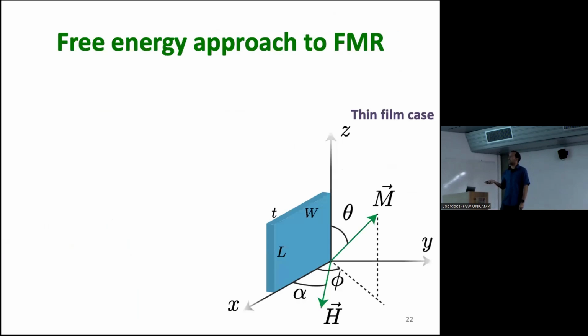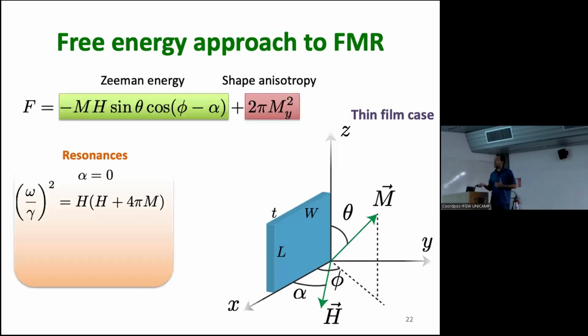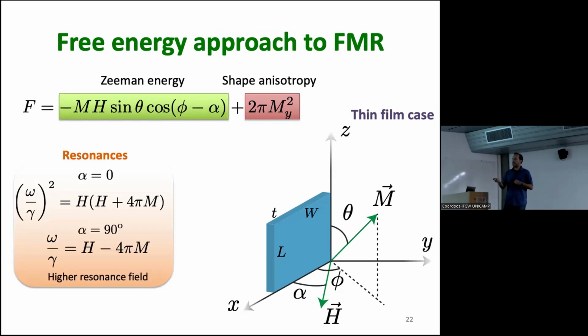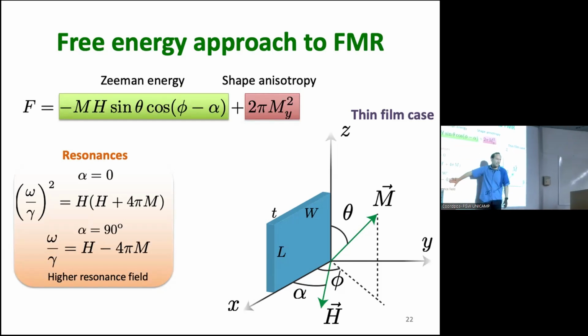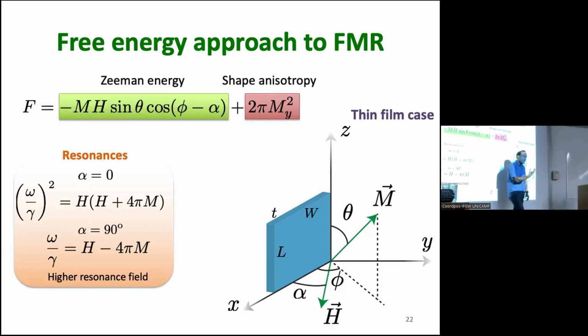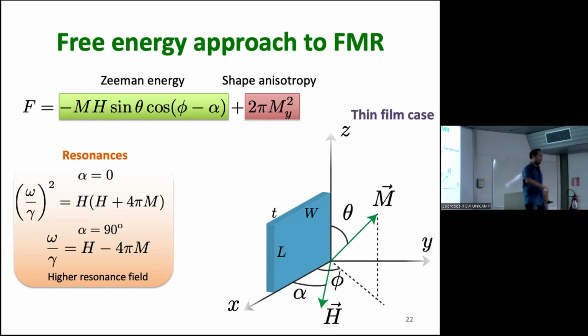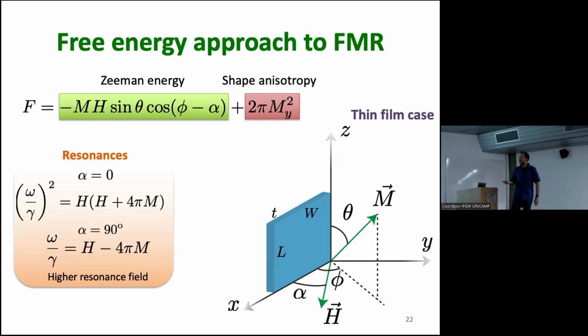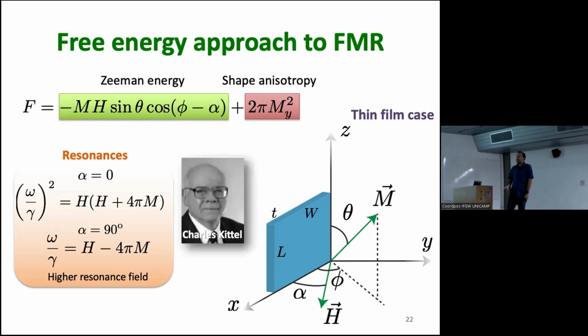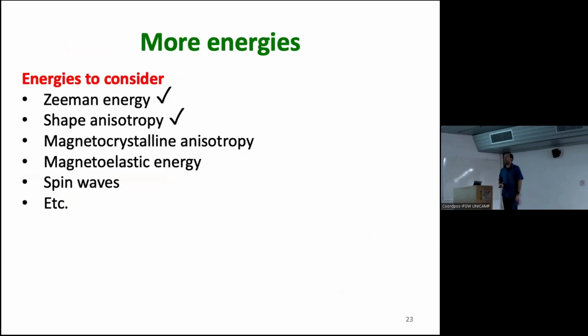So we did some. This is just for the students. By looking at the resonance, so at what field you actually get a resonance, you will gain a lot of information. If you put in your free energy, you can work out what the resonance frequency will be, and then you can check what your magnetization is. This magnetization has inside all the interactions that you can think of. Everything that happens in the sample will be in this parameter here. Okay, this is thanks to Kittel, one of the pioneers of the FMR and EPR techniques.